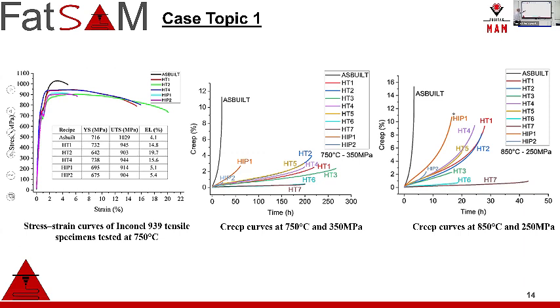We increase the UTS to around 900 megapascal, still lower than as-built, but the elongation values, especially HT1, HT2, and HT4, are directly oriented to vacuum heat treatment, controlled heating, and controlled cooling. I explained a little bit with HIP, but I didn't explain vacuum heat treatment. What is vacuum heat treatment?